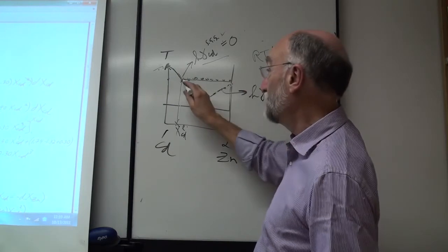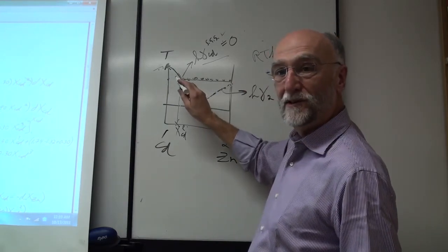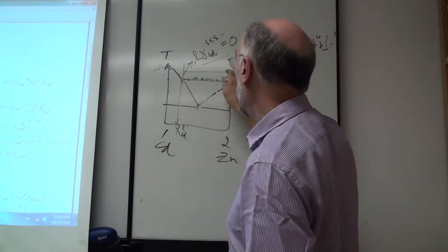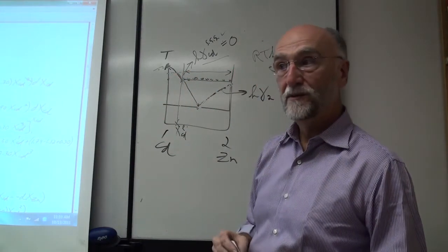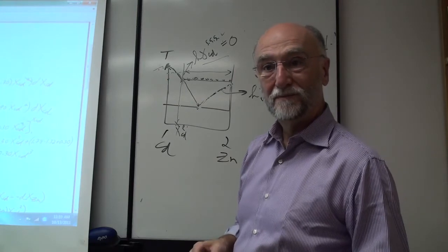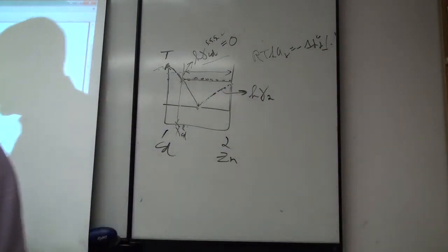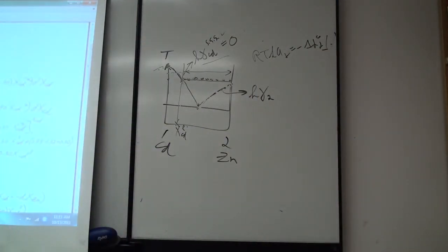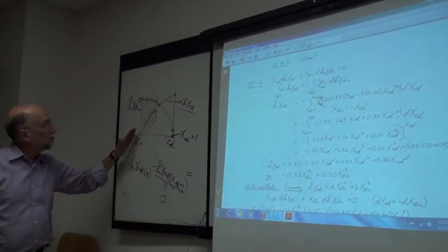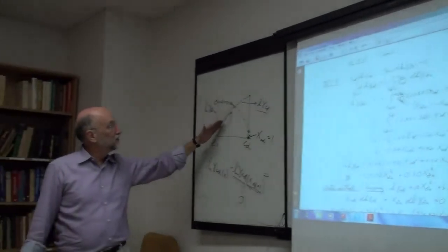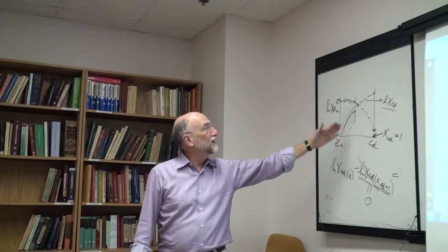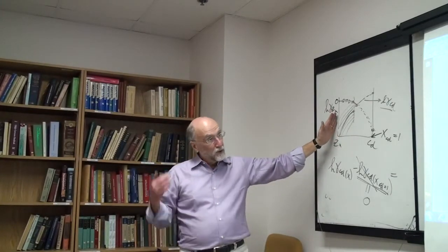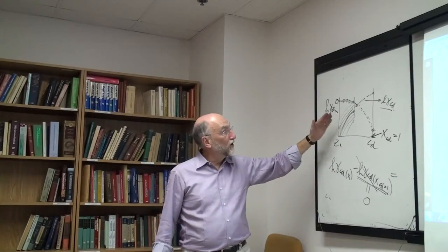Okay, but I'm using this endpoint. And then my log gamma cadmium, again, only applies strictly over this region and does not apply down to that region. So you see that when you're doing this, you have to look at what range my log gamma zinc has been measured, and my log gamma cadmium is then really only known over that region, give or take a constant of integration. I might have some known value of log gamma cadmium in that region, which permits me to fix my constant of integration, or I might not.